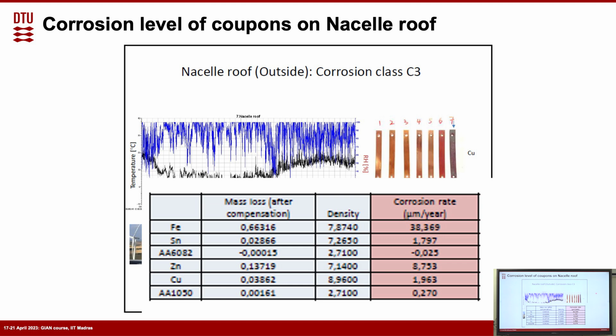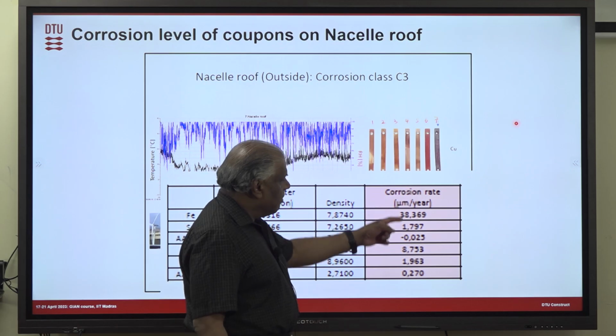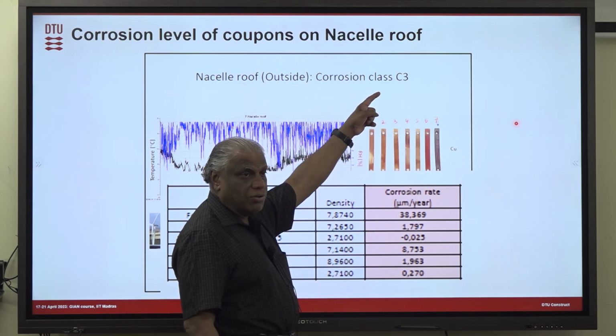If you look, you get quite a high corrosion level here, especially for the steel, around 38 micrometer per year, and that's what you get on the nacelle roof. But the important thing is that I put this slide, and I'll show you another slide as well, to see how it varies in the same wind turbine. So this is outside, and here you can see that from the level of corrosion we can determine the corrosion class. Corrosion class is C3.